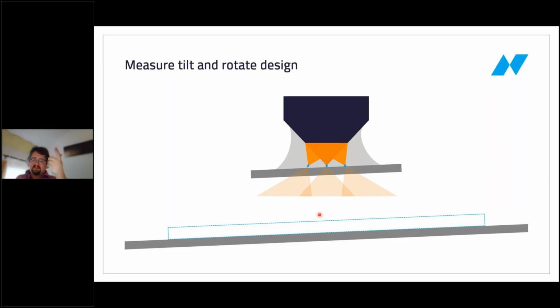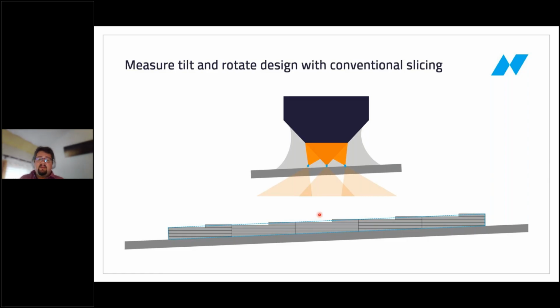So the slicing doesn't happen before the print, but actually during the print, and it happens in accordance with the correct tilt to the structure. So if you would do this with a conventional 3D printing approach, you could again achieve a good adhesion everywhere, but you would again get some discretization errors for a finite slicing height. So again, you would have some kind of steps in these features, and those steps would be in different positions depending. So this would also be quite far from a perfect solution.